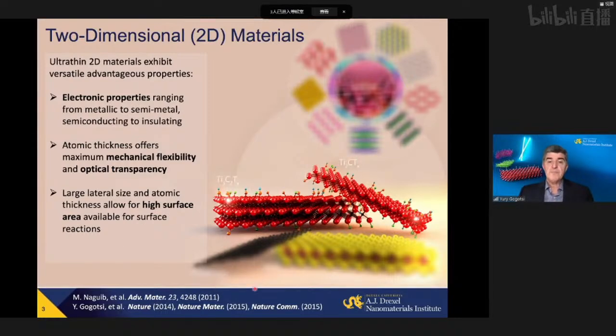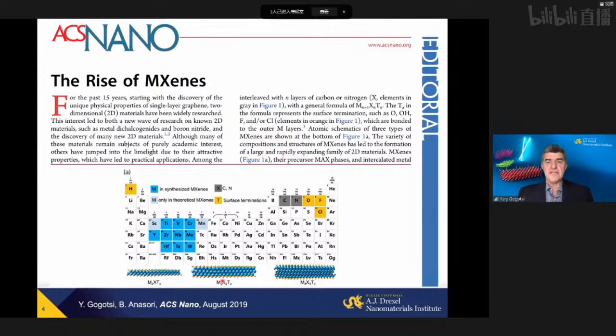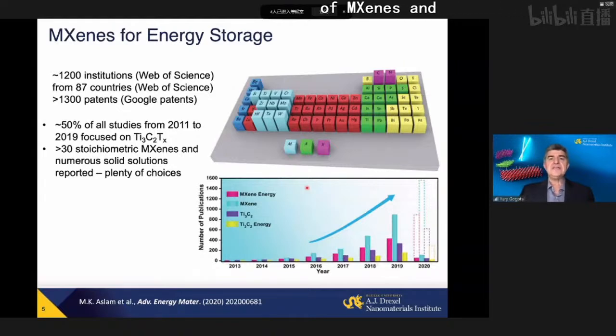And in 2011, MXenes entered the scene, first slowly, and then they started to accelerate quickly. They're really on the rise now, with more than 30 stoichiometric compounds between these M metals and carbon and nitrogen available, and a dozen surface terminations. I showed the first ones here, like oxygen, OH, fluorine, chlorine, but chalcogens, halogens, and others have also been shown: bromine, iodine, tellurium, sulfur, selenium on the surface. There are more than 100 stoichiometric simple structures possible. Multiply by 10 different surface terminations, you get more than 1,000. Take solid solutions, you get an infinite number.